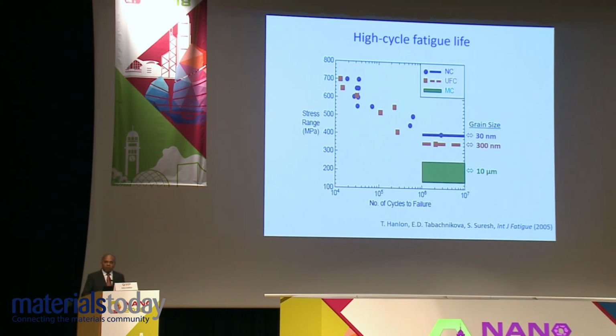But one of the problems with this is, first of all, you don't get enough of a big specimen to do mechanical loading that is required, minimum specimen size that's required to do a valid fracture experiment or a fatigue experiment. So now let's see what nanostructured materials do, how they behave when it comes to fatigue, which is one of the most critical practical applications and one of the most challenging as well.